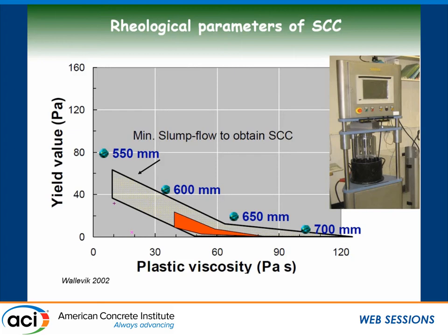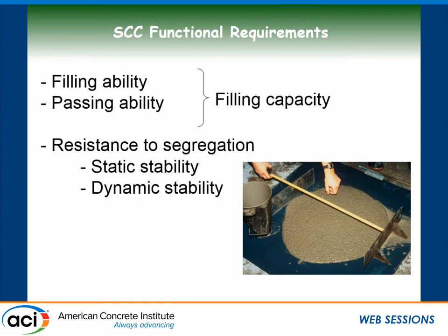Here you see that as the yield stress decreases, so does the slump flow of the concrete. The concrete becomes more and more fluid, going to 700 millimeters. If the concrete is very fluid, i.e. the yield stress is very low, you have to build in viscosity to ensure good suspension of all the solid particles and reduction of settlement. We don't use rheometers on site. We usually use robust, field-oriented test methods that measure all the properties I alluded to.